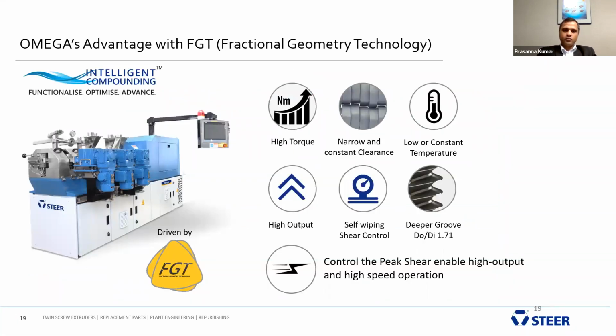So with FGT, we also have the platform called Omega platform, which is 1.71 OD by ID, which has the specification of higher torque. And also the clearance between screw to screw is reduced. When I say clearance, it is between screw to screw as well as screw to barrel, which results in constant temperature because of better self-wiping action. And since it is 1.7 OD by ID, throughput can also be increased for low bulk density and shear sensitive material. As I said, it has self-wiping action, which has better shear control.